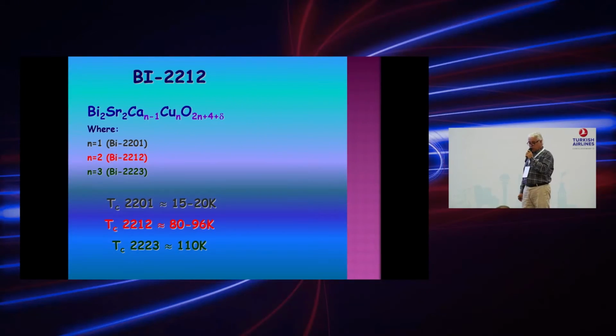Later on, we prepared the fibers of sodium, and after obtaining the optimum condition for sodium inclusion, we decided to add some silver, metallic silver, in order to enhance the superconducting properties.